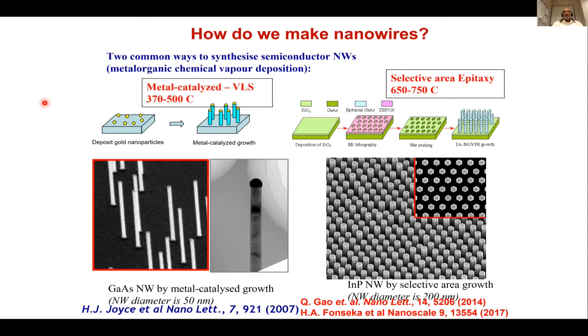In the case of the metal-catalyzed VLS growth process, we introduce some nanoparticles of gold on top of a semiconductor like gallium arsenide, typically about 50 nanometer gold nanoparticles. Gold has a melting temperature of more than 1000 degrees Celsius. But once the gold reacts with the gallium or aluminum or indium, you create the gold-gallium eutectic liquid, which has a melting temperature as small as 350 degrees Celsius. Gold-gallium, gold-aluminum, and gold-indium alloy temperatures are much, much smaller.